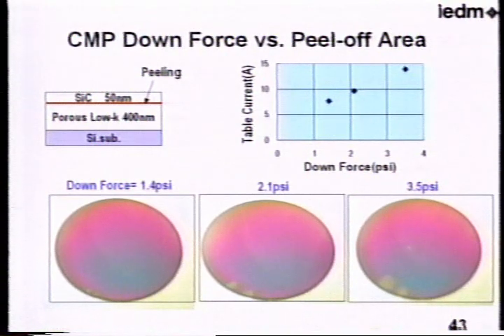And this figure represents CMP downforce vs delamination area of capping layer. The sample structure is like this. We did this CMP experiment by changing the downforce from 3.5 to 1.4 psi. With reducing downforces, you can see the area of delamination is much reduced. And also note that the starting point of delamination is at the wafer edge. So to reduce this kind of defect, we should take care of some treatment of surrounding wafer edge treatment, and also this kind of process improvement.